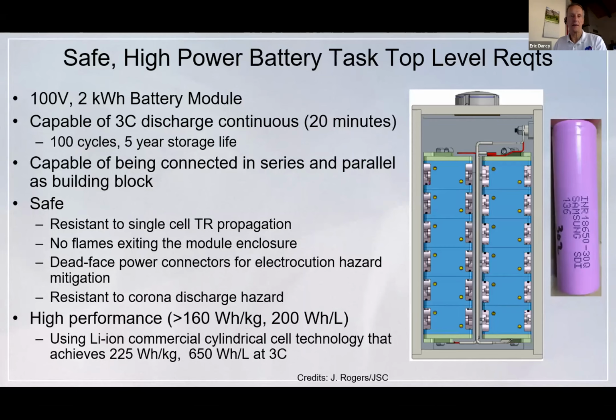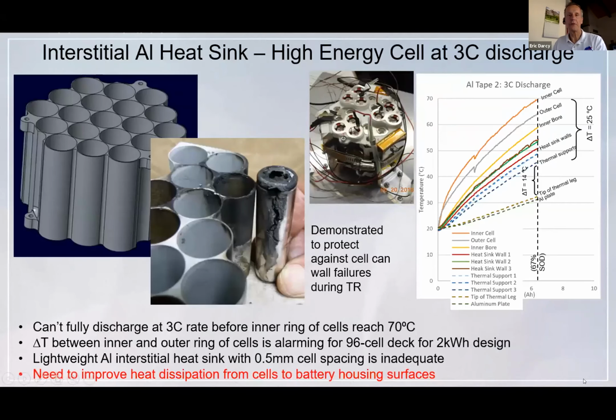Our baseline is to use commercial cells that are readily available for users that achieve the requirements here. From our database and previous experience with high energy packs, we went with an interstitial aluminum material that provides good heat conduction and also provides support for the cans when they misbehave and go into sidewall rupturing, as opposed to venting out the top or the bottom. When you have a sidewall rupture like I'm showing here, you can defeat pretty much all the features that you've placed in the battery to prevent propagation. And so you need to handle that failure mode first and protect against it.